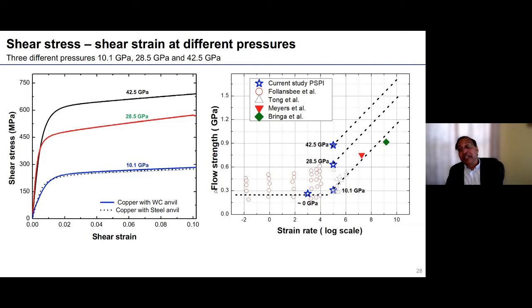We can look at the flow strength as a function of strain rate. What people have done is that, as I mentioned, our strain rate is nominally constant, about 10 to the power 5 per second, but we are varying the pressure. So we are fixing the strain rate and looking at the increase in the pressure. So we are establishing the pressure dependence of the flow strength, and as a function of strain rate, as you know, there's this strong upturn.